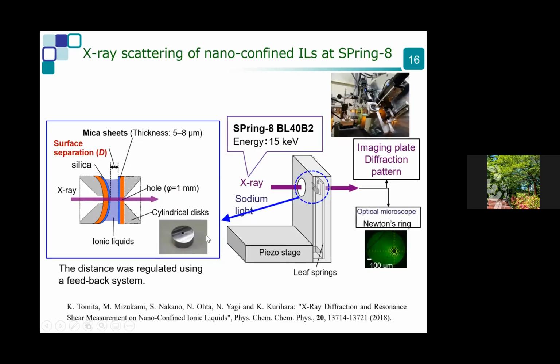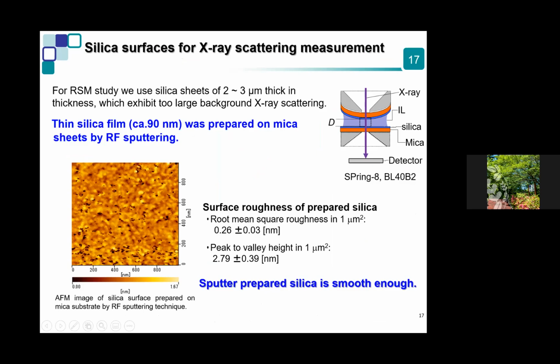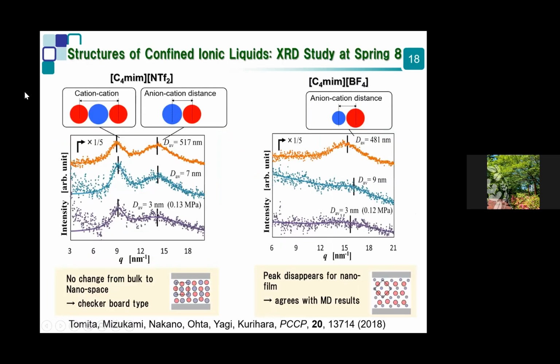And we studied X-ray diffraction from such systems using a very thin silica sheet on mica. We could sputter such a silica sheet on mica, and this is to avoid large background X-ray scattering. And the signal obtained for a 3 nanometer thickness film is shown here, which indicates such alternate alignment of ions. But in the case of BF4 minus, this peak disappears. So this structure agreed with such alternate layering of different ions.